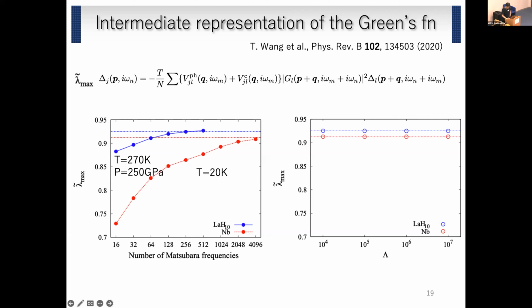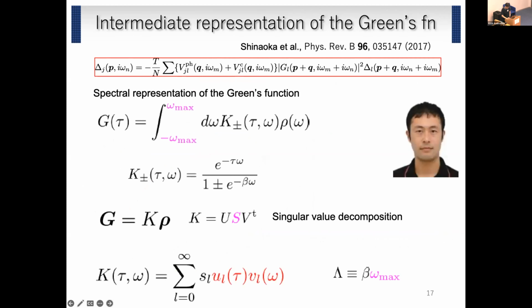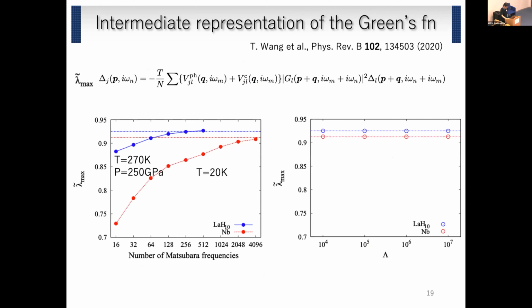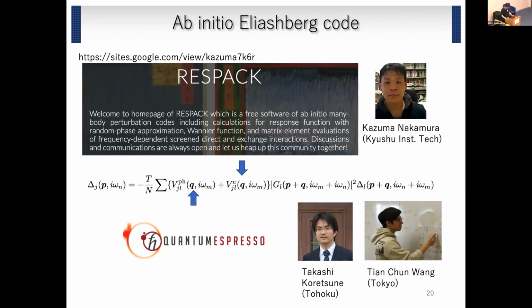And we do the same calculation using the intermediate representation of the Green's function. And in this case, sorry, this lambda is this cutoff. And even though lambda becomes large, the Lmax, the number of bases required to represent the Green's function, is always 30 or 40. And we see that the result doesn't change. And so with a very small numerical cost, we can solve this Matsubara frequency Eliashberg equation. And so we implemented this scheme, and we solved this Eliashberg equation.